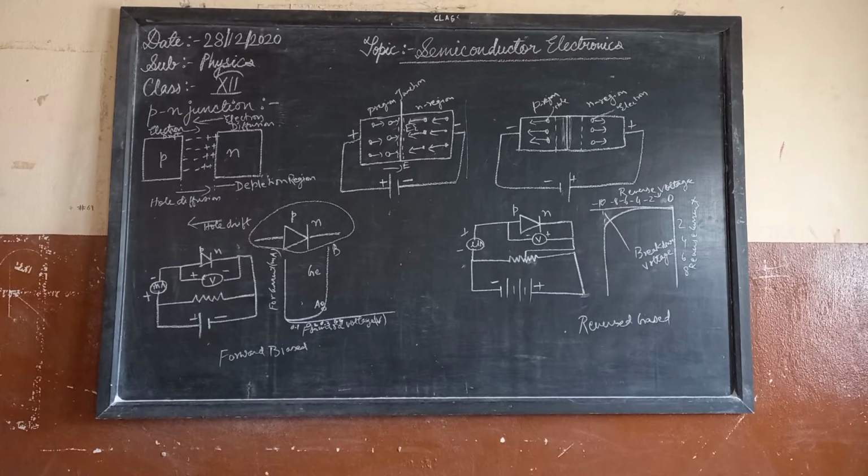In the junction arrangement, by close contact of N-type semiconductors and P-type semiconductors, there are various methods of forming a P-N junction. In one method, an N-type semiconductor germanium crystal is cut into two slices called wafers, and an aluminium film is laid on the N-type wafer, which is then heated in an oven at a temperature of about 600 degrees centigrade. Aluminium then diffuses into the surface of the wafer. In this way, the p-n junction is formed.